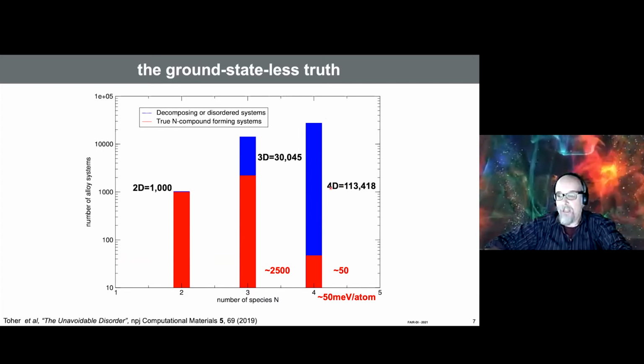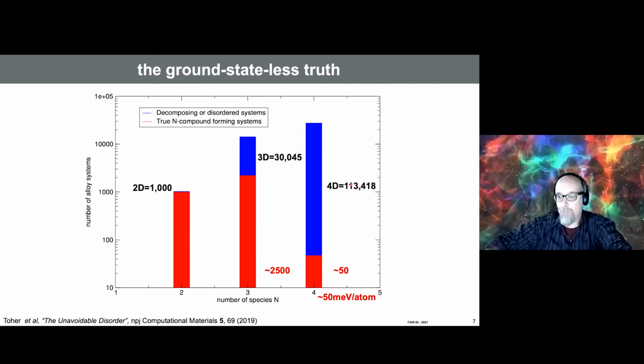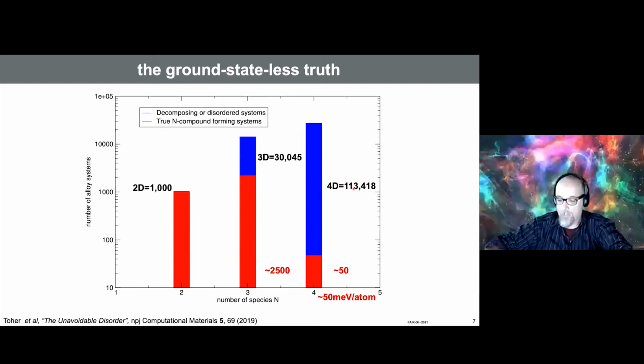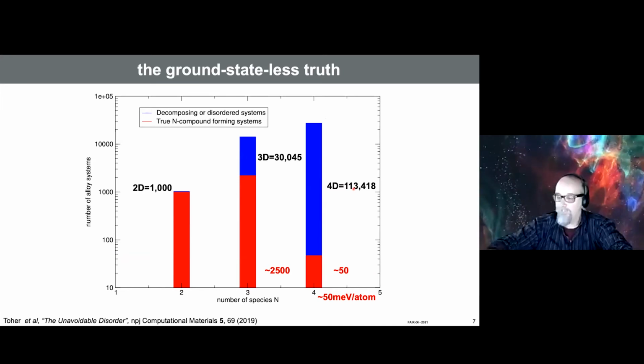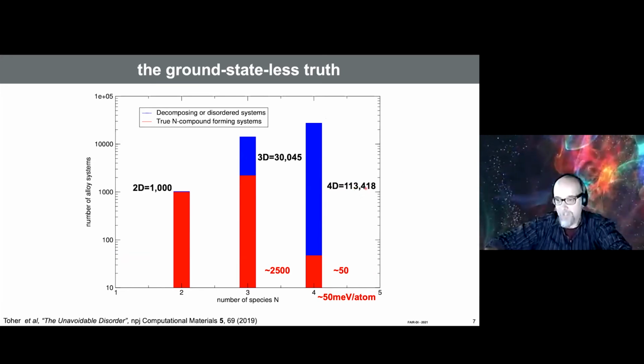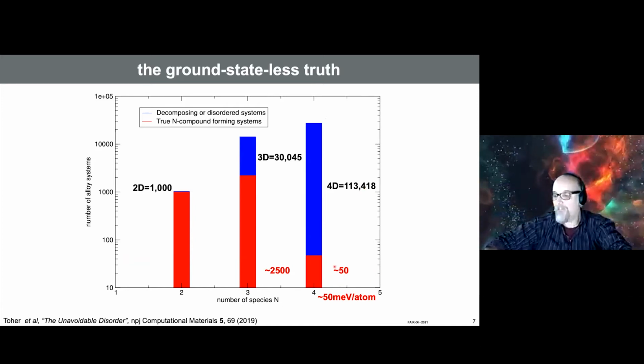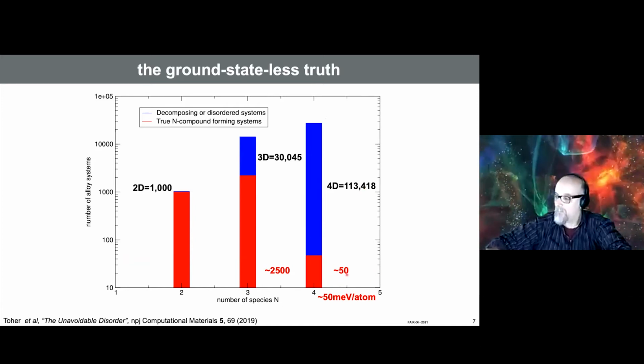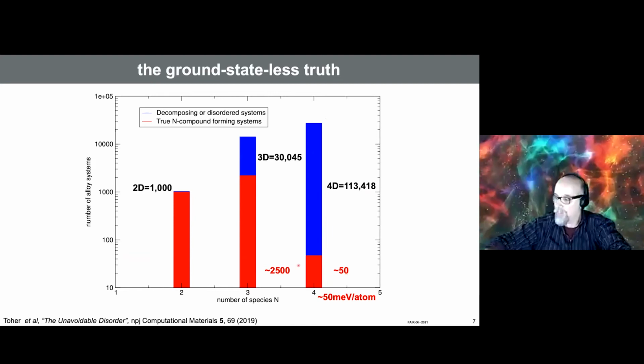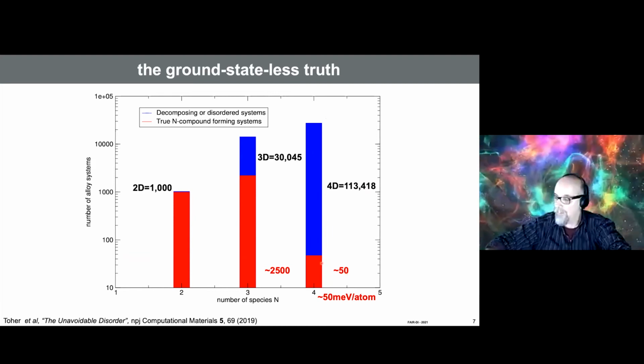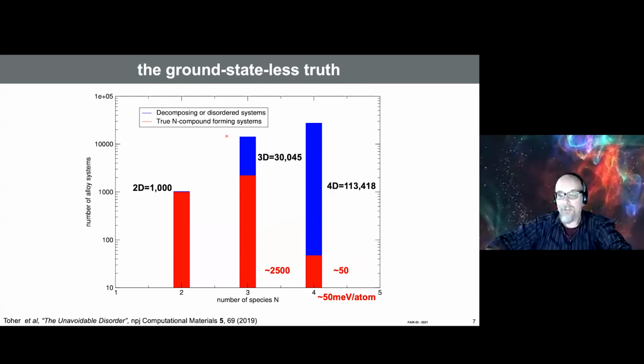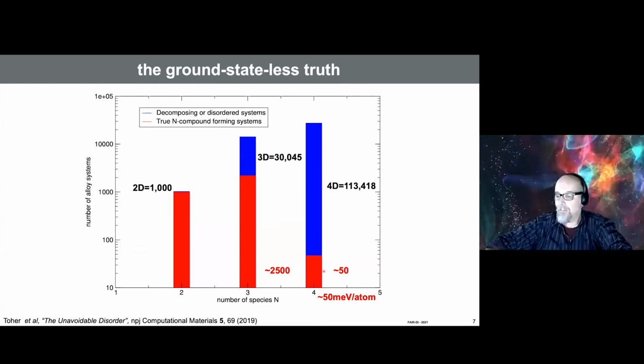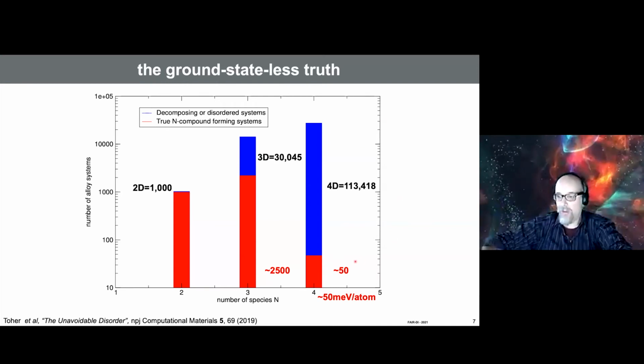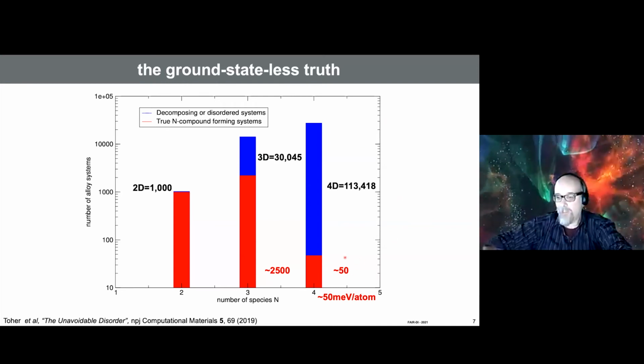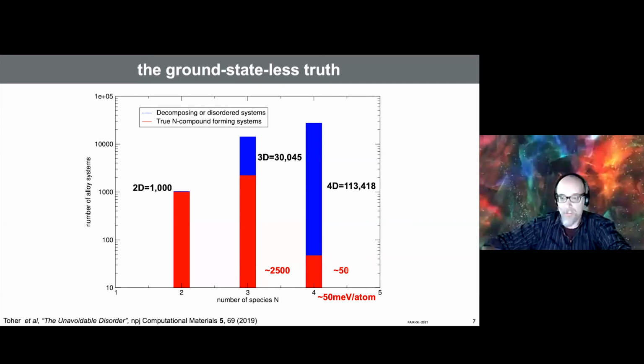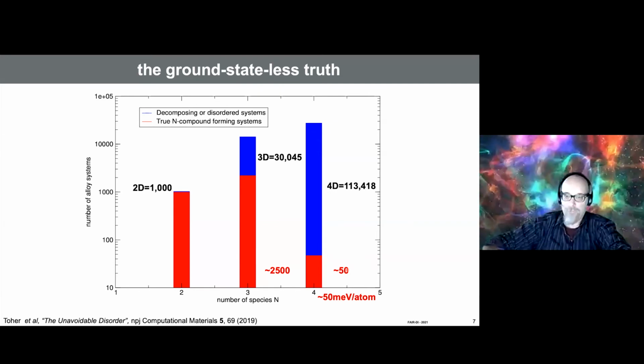If you take 4-species systems, and we have 113,000 phase diagrams, and you can reproduce this with Nomad, you would even get more than 100,000. You will find that only 50 of them actually have stable configurations that are ordered, right? You see how the red versus the blue, the red shrinks dramatically, and this is a log plot, right? So that's why you just say, well, who cares about these 50, and you just embrace disorder and find what you can do with disorder.